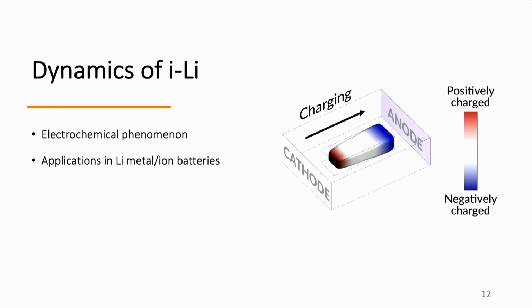How can we use this kind of phenomenon in real applications? Here I want to give you 3 examples. The first one is lithium metal batteries, where we actually studied it. To utilize this kind of fundamental research, we developed a new charging protocol to implement this understanding. Not only do we want to charge the battery, but we also want to implement a short, fast discharging step to recover the previously lost capacity. By doing so, during every cycle, we're using about 4% of battery capacity, but in the long run, we're extending the battery lifetime by 30%.